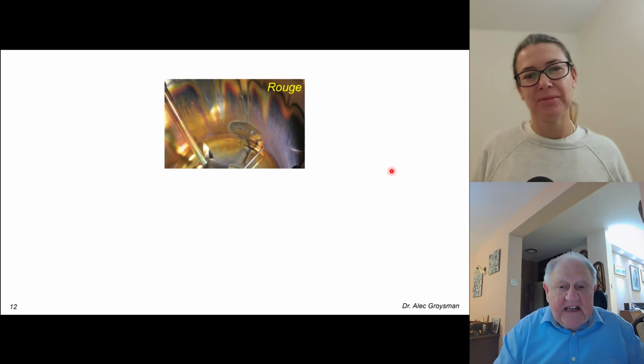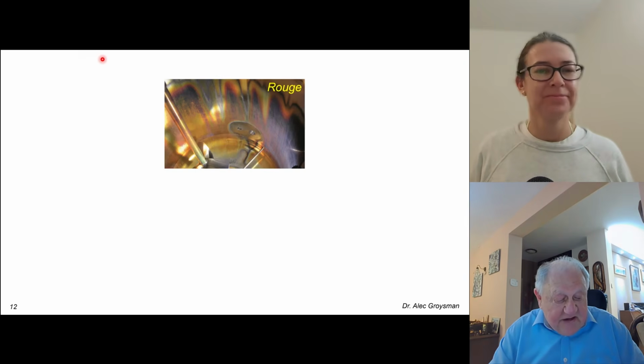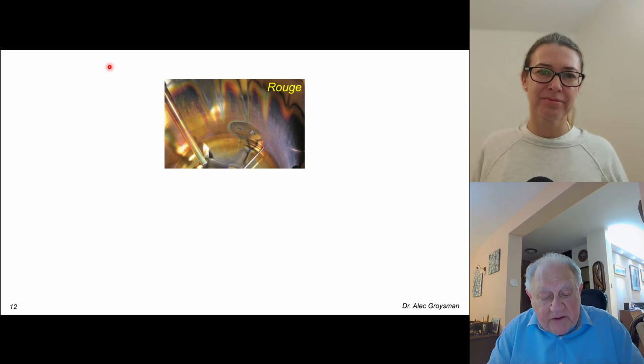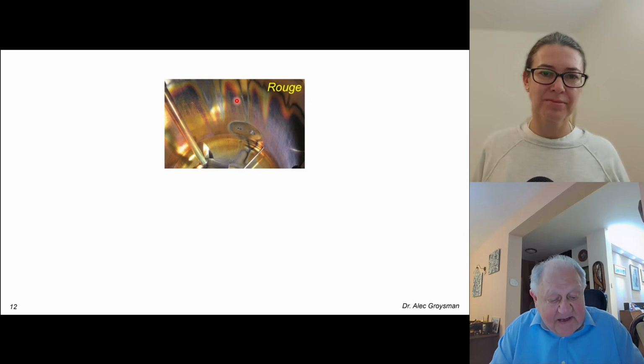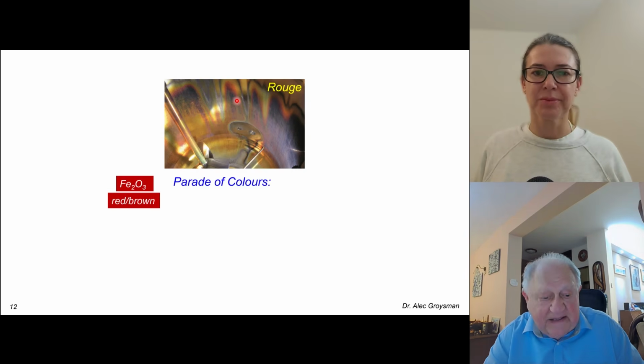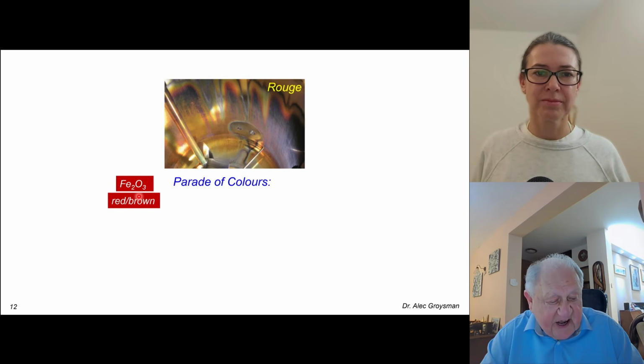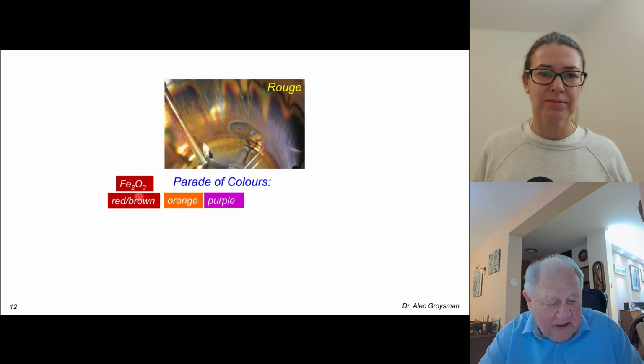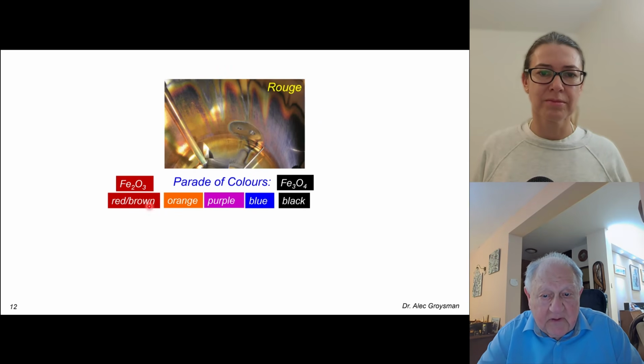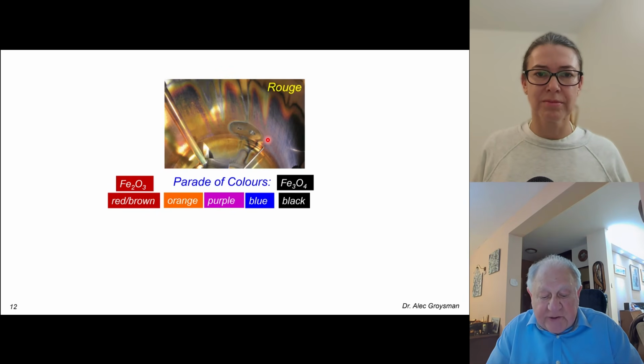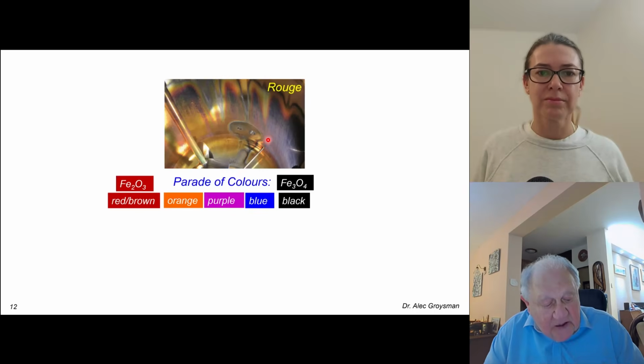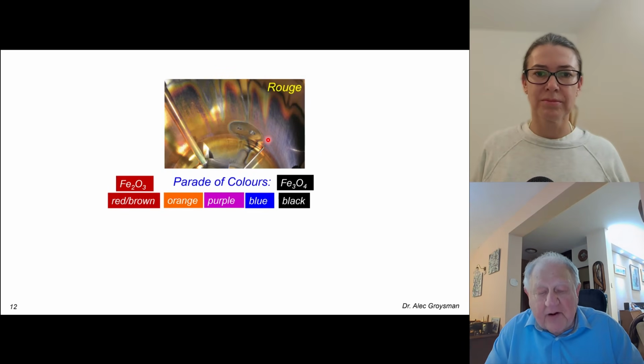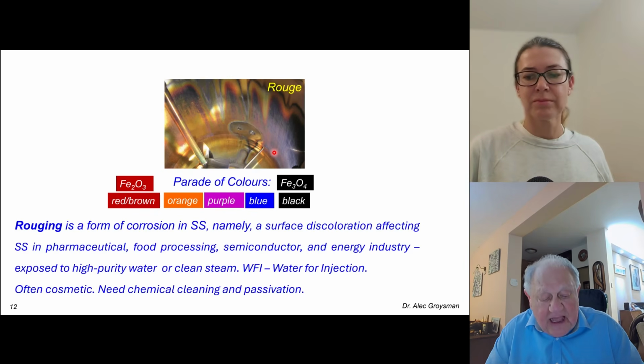Rouge is the commonly used term for the visible corrosion product of stainless steel. It can be composed of several forms of iron oxides, with red ferric oxide being the predominant form, maybe orange, purple, blue, and black, Fe3O4. It can be due to iron contamination of the stainless steel surface due to welding of non-stainless steel for support clamps or other temporary means, which, when welded off, leaves a low chromium area.